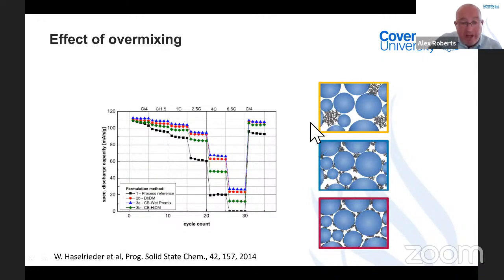where you've got some connection between some of your active materials. If you get your dispersion right, you end up with the second image, where you've got some dispersion of your carbon black, but it can come back together and it can form these chains between the active material particles. So you get a network of connected particles. They're connected by the backbone, the conductive backbone from the carbon black.